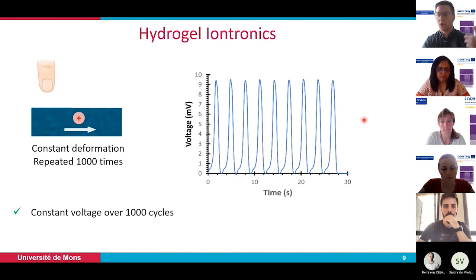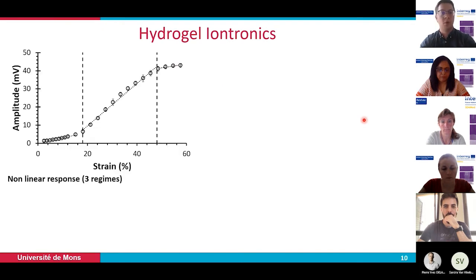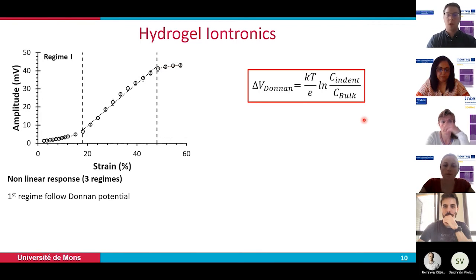What happens when you change this deformation? First of all, we look at the amplitude as a function of the strain. But what we can see is that we have a nonlinear response, with 3 regimes that can be explained. First, at small strain, we are in a Donnan potential regime. So this is the first regime. There you have only a difference in potential due to the modification of ion concentration at different spots inside your material. So this follows this Donnan potential.